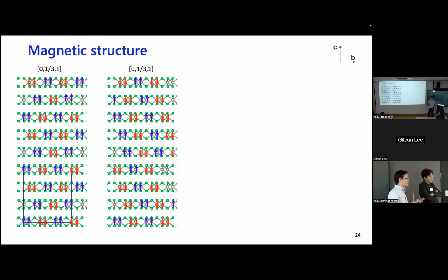I was thinking about the crystal structure; I don't think there's information on that, but the magnetic structure is changing. As you apply fields, your magnetic domains are killed, and then you gain a single magnetic domain structure, or a spin flop transition happens at around 1 or 2 Tesla. Beyond that, at about 6 Tesla, there's a neutron scattering result from Oak Ridge that says the magnetic structure changes.